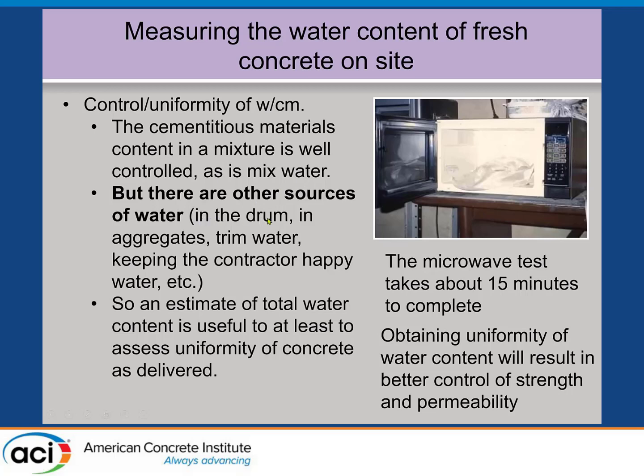There's water that was left in the drum from the previous load. The aggregate water is not always well defined or well measured. There's trim water added to get the slump up. And then what I call keeping the contractor happy water when it arrives on site, because the driver wants to get along with the contractor. So the microwave test at least offers a way of looking at the uniformity of the water.